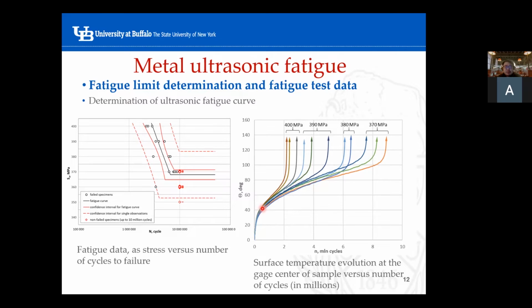In phase 2, which is the approximately linear stage, we have steady heat generated due to internal frictions and microplasticities, and we also have local heat loss due to conduction of heat with the environment. So at this stage, we have a steady increase of temperature.